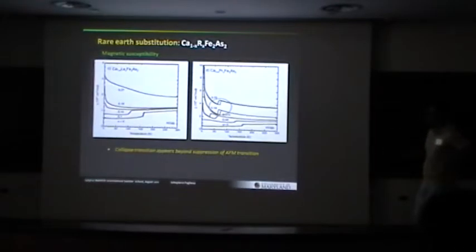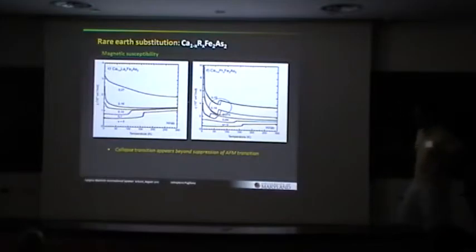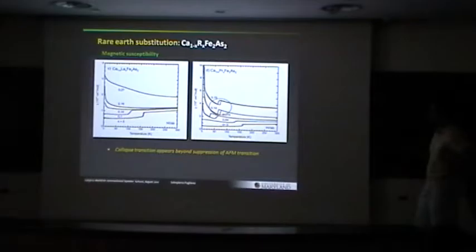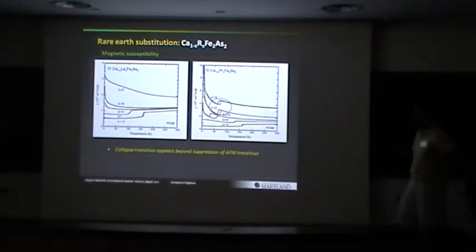Okay, so going on to some physical properties to finish up. This is a lanthanum doped series. This is a praseodymium doped series. This is magnetic susceptibility to temperature. You can see the undoped compound undergoes this well-known structural and magnetic transition. As you put lanthanum in, it's suppressed, and this is more or less featureless. There's a bit of a tail here, but it's not very interesting. The praseodymium sample, on the other hand, undergoes this very strong collapse, and that's indicated by these hysteretic drops in susceptibility that first appear here, and then they march up a little bit in temperature as you put more praseodymium.